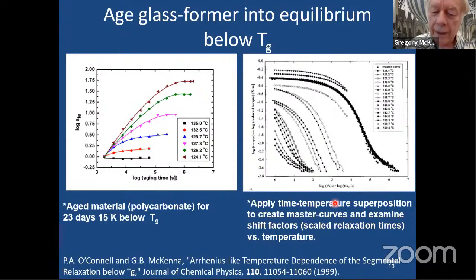And in 1999, when I was still at the National Institute of Standards and Technology, Paul O'Connell and I did some experiments on this polycarbonate where we did the aging. Here we see, at different temperatures, these are like the intrinsic isotherms of Kovacs, except in shift factor. As we go to lower temperature, things take longer, and shift factors get bigger. We're only about 10 or 15 degrees below the glass transition here, and this experiment took 23 days or something.